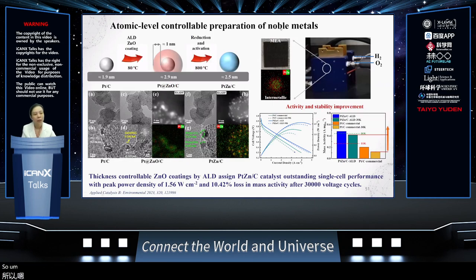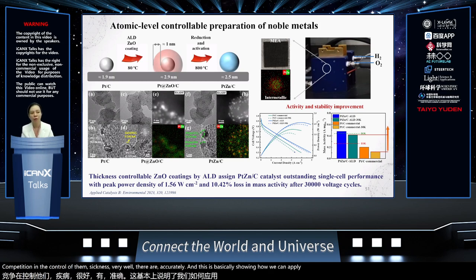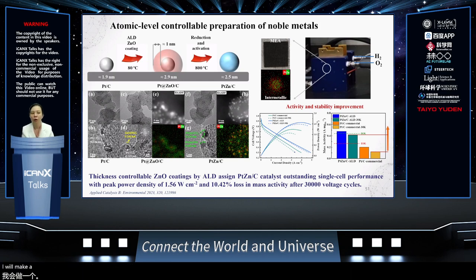The last one is utilizing similar ways, we are able to form a very nice platinum zinc catalyst on carbon. And this catalyst is good for fuel cell applications. Why we want to do the ALD coating and then convert it is that we can decrease the amount of platinum, and also form these platinum zinc alloys very well. If you do wet synthesis, normally you will get much larger particles. If we do it like this, we can control the composition and thickness very accurately. This shows how we can achieve atomic control of the composition and the structures.